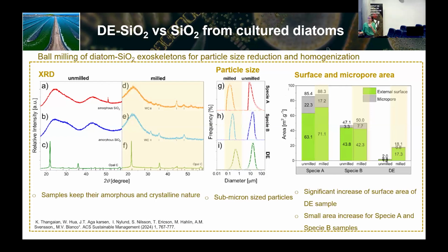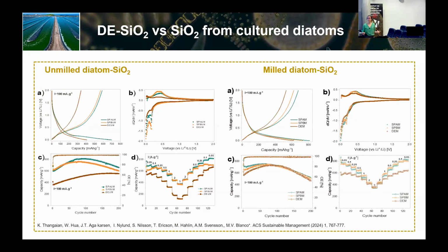So this actually is a good thing, because it might be that in the future it won't be necessary just to do the milling of the material. So then we made cells, and then we compared what happened with the material. The first thing that happened is that instead of 5 cycles of activation, we needed 1. And with 1, we still have this capacity gain, but it's not super high as before.